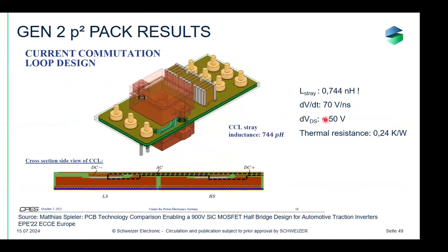This was one of the projects that we did together with Virginia Tech with the Center for Power Electronics. So there's a nice publication about it. If you're interested in it, I can also provide it to you. We made such a P-squared pack for double-sided cooling, which was special. So there was a heatsink at the top, and there was a heatsink at the bottom. We achieved a very low stray inductance of 0.74 nanohenries. So we are talking about picohenries today, not about nanohenries anymore. We had a very, very fast switching of 70 volts per nanosecond. And by doing this, even with this high speed of switching, we achieved an overshoot voltage of less than 50 volts.